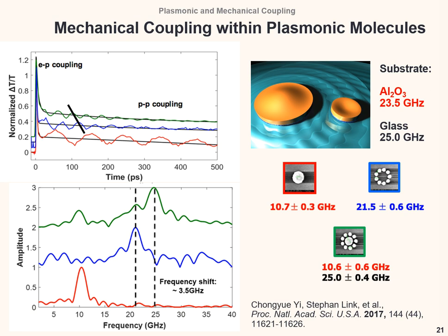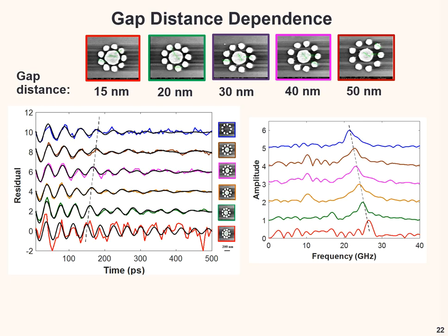What I have studied is that if we have nanoparticles sitting on the surface of a substrate, nanoparticle vibration will generate this surface acoustic wave, and this surface acoustic wave will feed back into the small nanostructure and eventually couple. To prove this idea, when we change the substrate, the coupling strength is strongly dependent on that.